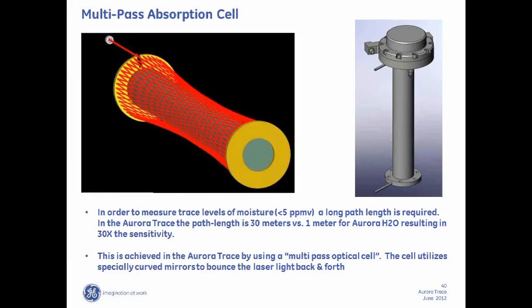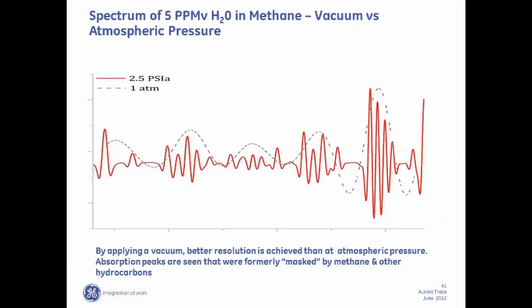So the effect of the pressure broadening is shown on this slide, and the dotted line is at atmospheric pressure. The same gas under 2.5 psia is the red line, and you can see that there's a lot more detail on the red line than what you had on the dotted black line. And that detail comes out as sort of like looking at a high-definition television versus a conventional television. You're seeing much more detail.